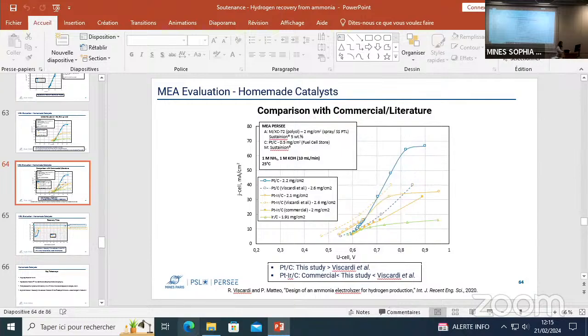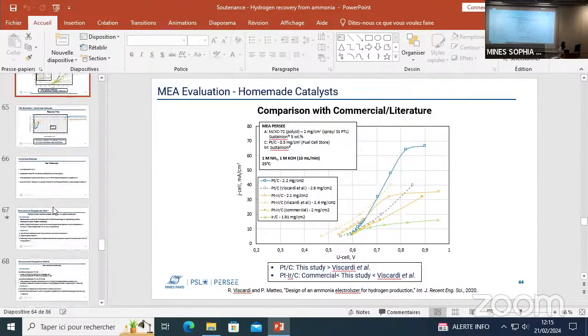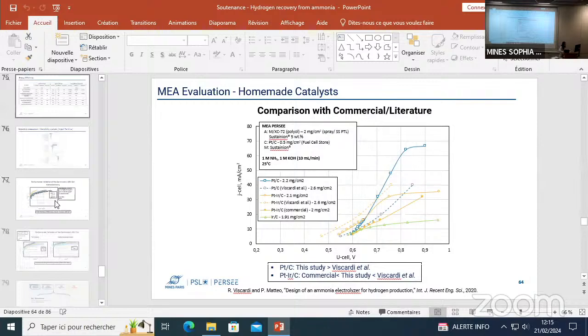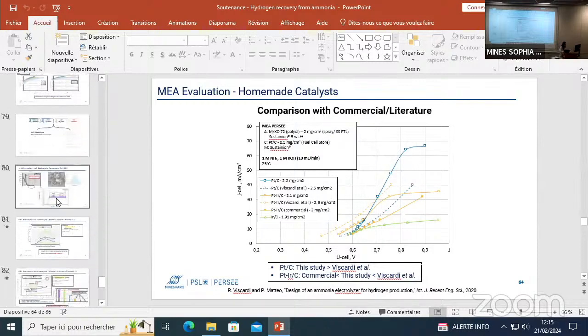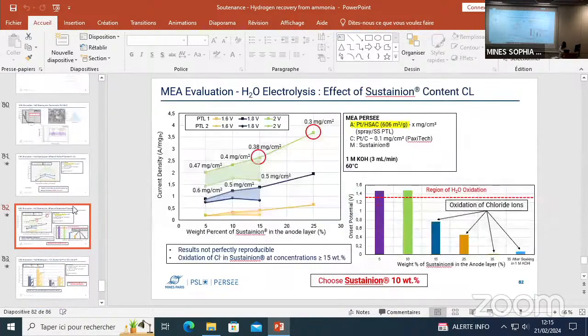I already did that, actually. I hope I can find the slide. Here, when I was studying the impact of Sustainion, you could see that at very high concentrations, if you look at the onset potential, for concentrations higher than 15 we have very low potentials which do not correspond to water oxidation.